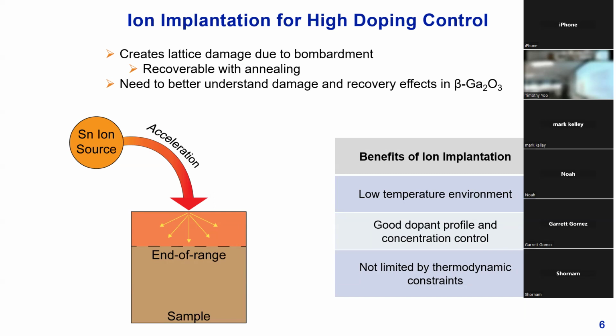It does come with the drawback of, as I just mentioned, lattice damage due to this bombardment of ions, but it is recoverable with annealing. However, we still need to have a better understanding of the type of damage that's being induced, as well as how effective those annealing parameters are.